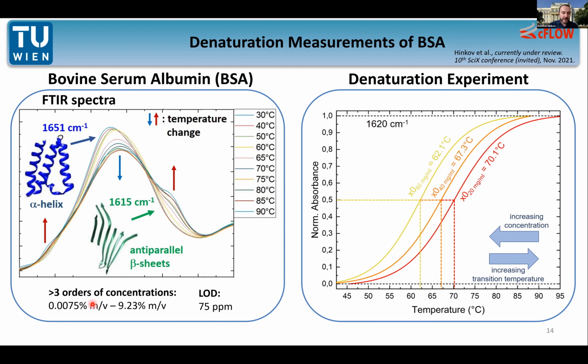Moreover, some other nice features of our chip are that we can cover 3 orders of magnitude in concentration, so we can really scan a wide range of concentrations. And the limit of detection is also, without doing anything specific to further optimize it, already very nice with 75 ppm.